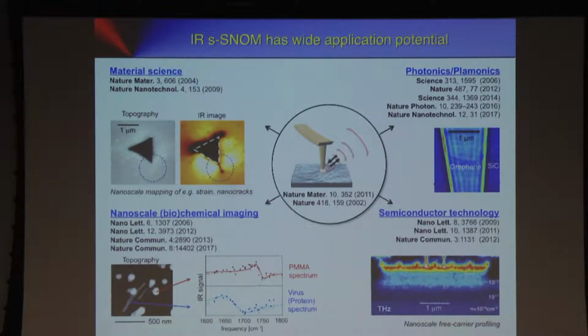What happens is that the lattice vibrations, the phonons, they shift. And because of that, we get an optical contrast in the near-field image. And what you see here in the bright areas are compressive strain fields, and this tiny little dark area here, which you don't see in the topography image, that's a crack where we have tensile strain. So I don't want to talk about that here, but that's an interesting application. Also difficult to get quantitatively out the strain fields.